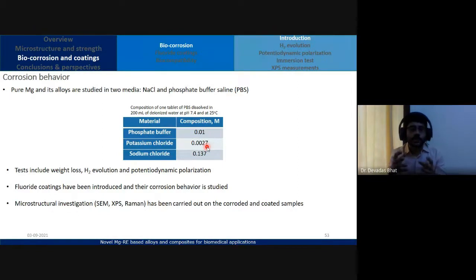You know that you can do what is called an immersion test, right? That is a weight loss. So you immerse your sample inside the electrolyte, take it out after 1 day, and do the weight loss. So how do you do weight loss? So you take the sample out, there will be some oxide forming on the surface, remove the oxide, and then you have your sample, whose weight is obviously lesser than that of your initial sample.